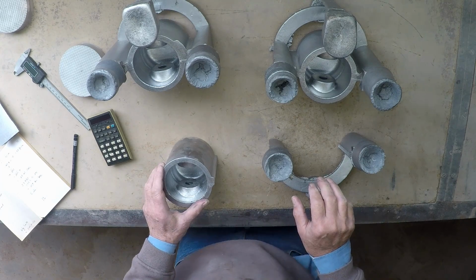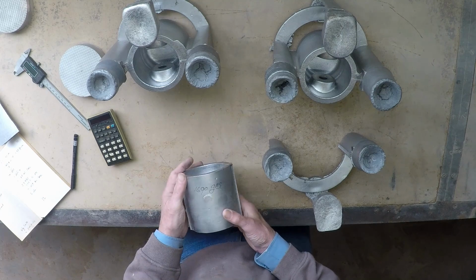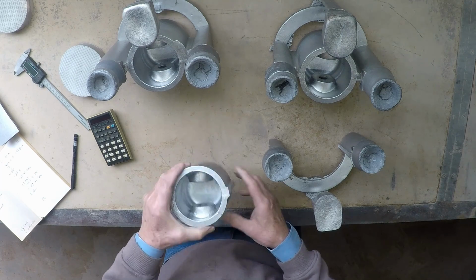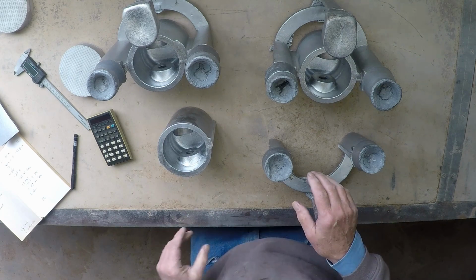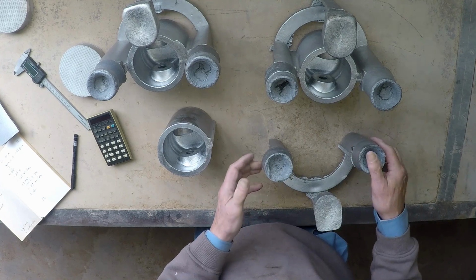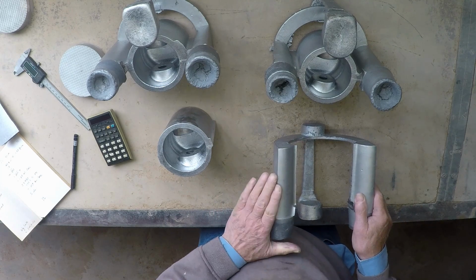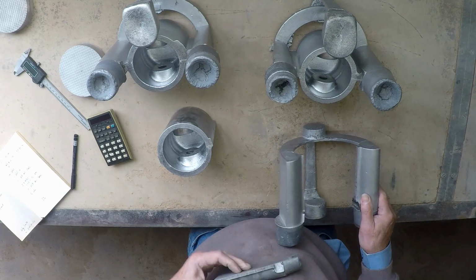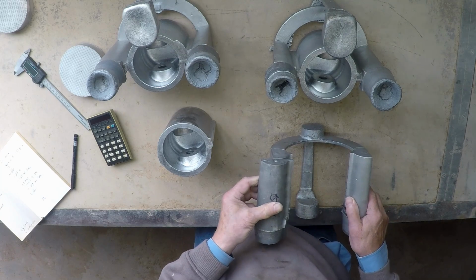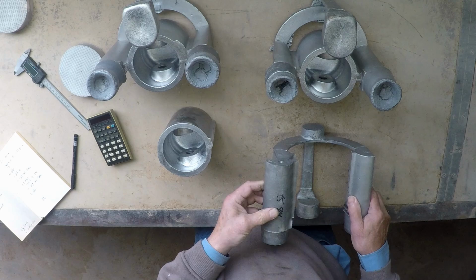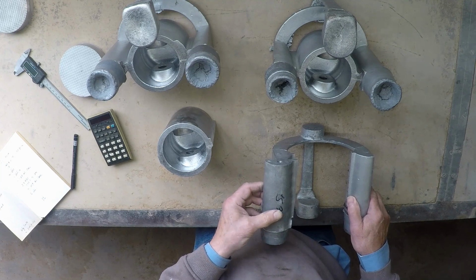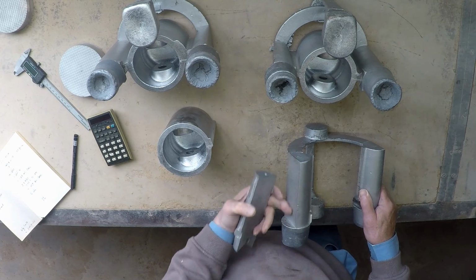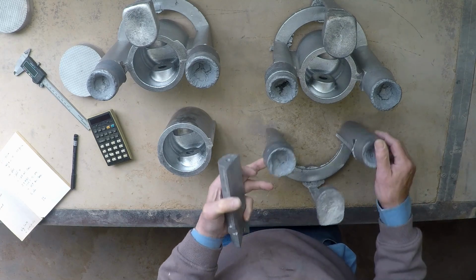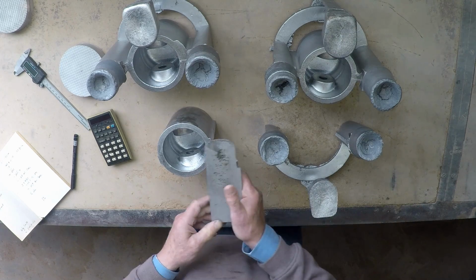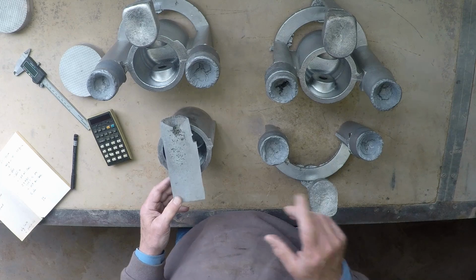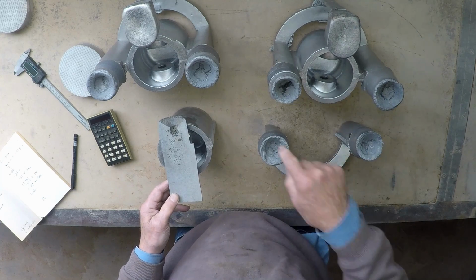we cast 4 kilos to get each one of these, and the piston itself weighs 1,690 grams, so the yield's not exactly great. We did, in fact, in an earlier one, use the side risers as a complete round like this one, and we decided that the yield then was even worse. It was a bit unnecessary, so we've ripped a bit off the risers on this one, the bit off the feeders. The only danger with that is that, as you can see, this alloy is renowned for very high shrinkage.